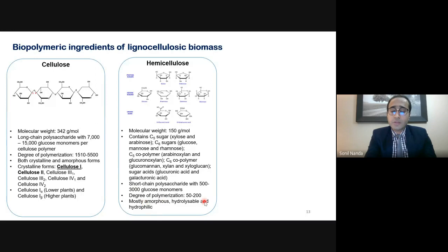Now, the degree of polymerization of hemicellulose is also much lower than that of cellulose. And because of the lower degree of polymerization and the short chain polymers, hemicellulose becomes amorphous, hydrolyzable, and hydrophilic, which means that it is easy to hydrolyze or remove hemicellulose just by boiling the biomass in hot water at 100 degrees Celsius.